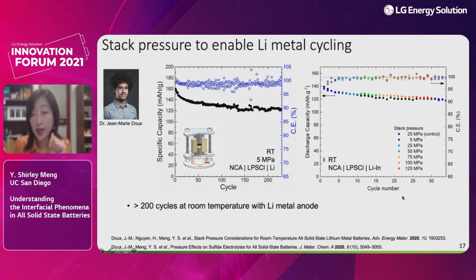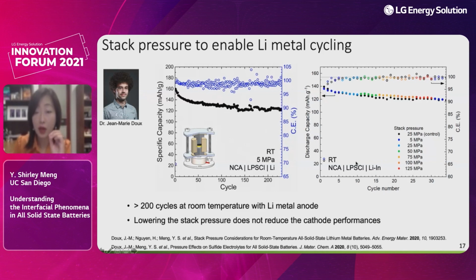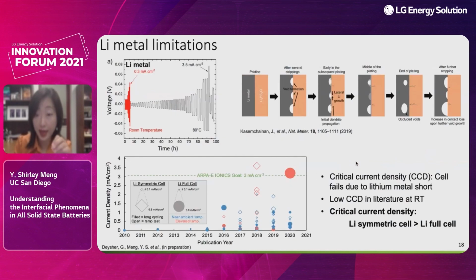If you look at the cathode effect, if you change lithium to a lithium-indium alloy, the pressure has almost no effect on the performance of the cells. So this really propelled us to think about an alternative anode strategy. And we know indium is not a sustainable solution because indium does have quite a high price tag.